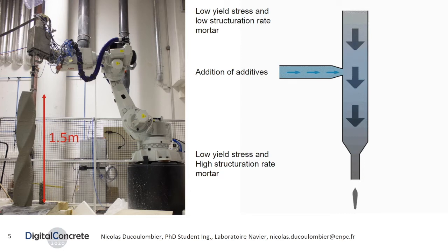One could eventually think of a pressure measurement, but it will rather give information on tribological properties rather than yield stress. Others propose to perform ultrasonic pulse velocity tests to evaluate the elastic properties at the nozzle, but it only provides qualitative information unless proper calibration procedures are made for each printable mixture. We therefore suggest in this presentation another universal method to assess the yield stress at the nozzle exit.